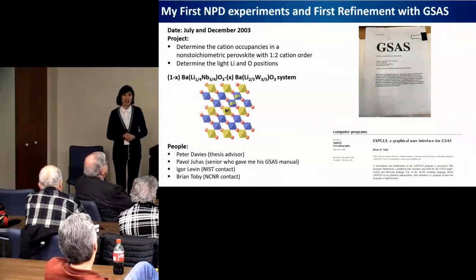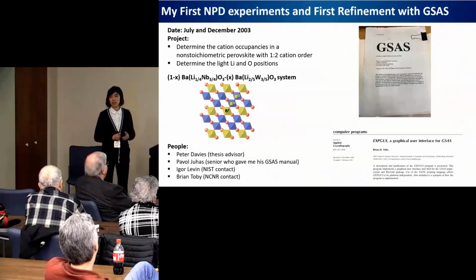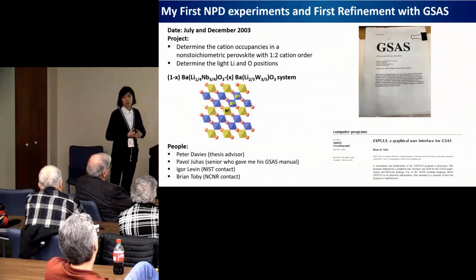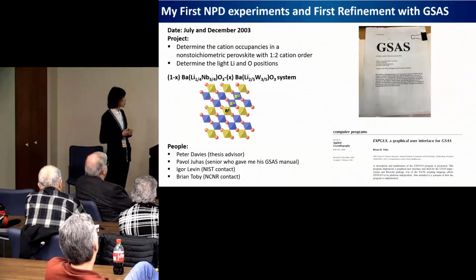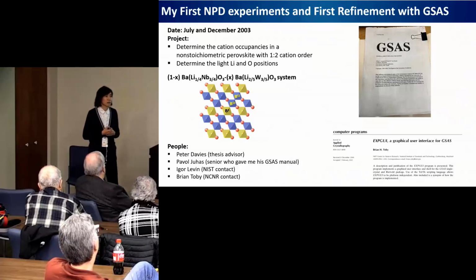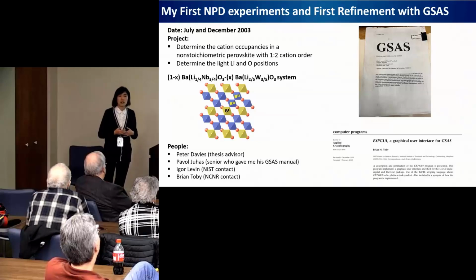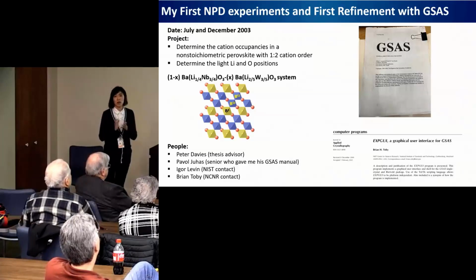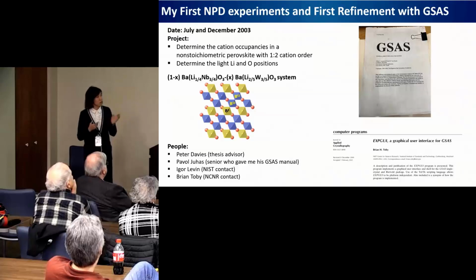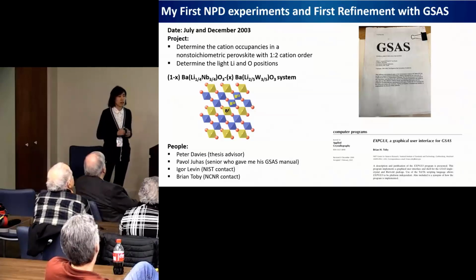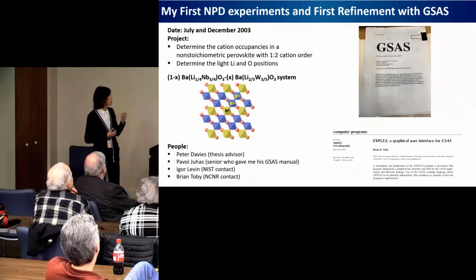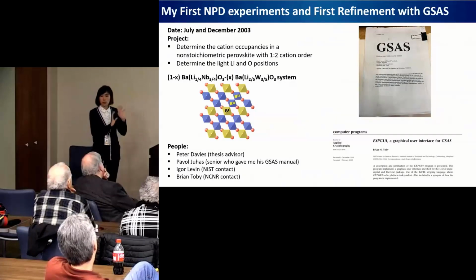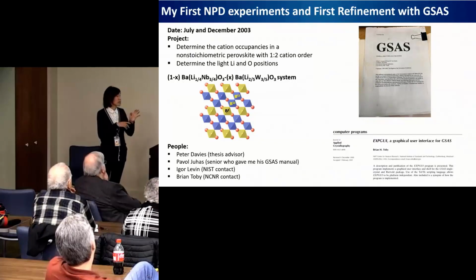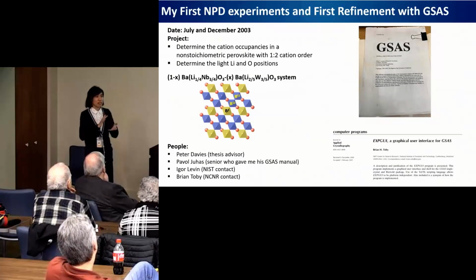Actually, I started to learn GSAS not very long ago. In 2003, I was still a PhD student with Professor Peter Davies at the University of Pennsylvania. We were working on some ceramics with perovskite structure, focusing on cation ordering and its impact on the dielectric properties of those materials. In particular, I was working on the barium lithium niobate and barium lithium tungstate binary system. Both end members are hexagonal perovskite with face-shared octahedra.